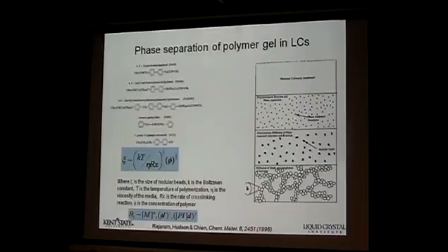If your surface is not clean, has some dust particles, they start to form those polymer networks from there. And then under the microscope, we can see those defects, a dark spot, right? Because it destroyed the alignment, and then you got the defects. So you see the defects under the crossed polarizers microscope, and you see dark spots, and then they start to grow, getting bigger and bigger, and finally forming a chain. When critical mass reaches a certain degree, these networks start to connect to each other.